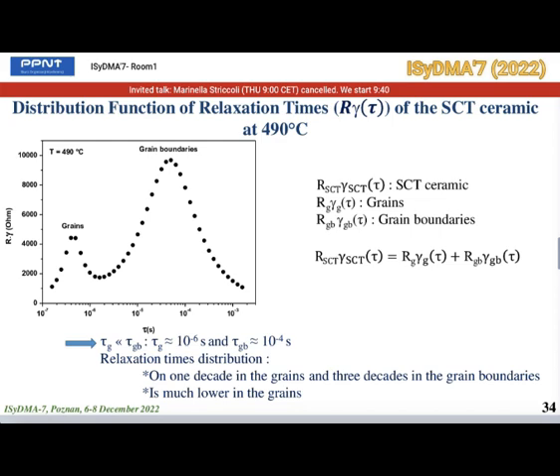We show here the R gamma evolution, where R and gamma are respectively the resistance and the DFRT of the ceramic, obtained by adding the DFRT of grains and grain boundaries. The distribution of relaxation times in grains is spread over 1 decade, and is much lower than that in grain boundaries, which is spread over 3 decades. This may be related to the fact that the relaxation times are more distributed in grain boundaries than in grains.